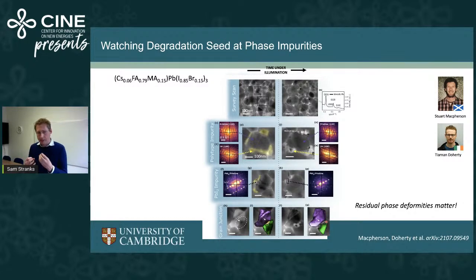So this is showing that these hexagonal polytypes seem to be degrading first, but then it starts to spread and starts to degrade some of the perovskite as well. So what we're seeing is that this is actually where the degradation, photodegradation, starts to seed in these films and in these devices.